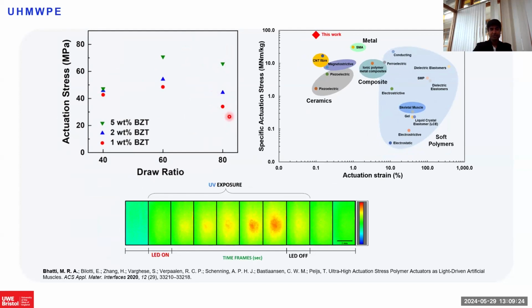the actuation stress gets down at a higher draw ratio. I would like to mention over here that the maximum draw ratio for any polymer material depends on the molecular weight of the polymer, the concentration of the polymers within the solution, and also on the processing route. So the maximum possible draw ratio with our parameters using ultra-high molecular weight polyethylene was around 100. So we thought that 80 is very much closer to the maximum attainable draw ratio.